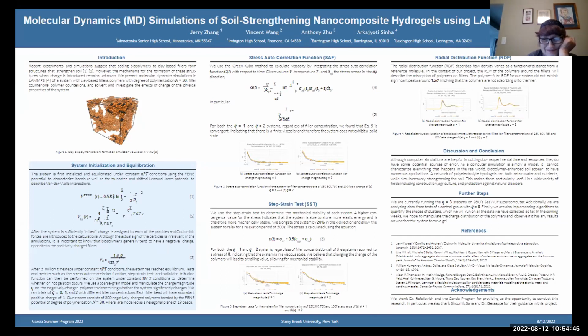Jerry. In addition to the experimental studies conducted on the use of biopolymers as a soil additive, our group seeks to characterize how charge induces the network formation of biopolymers and clay fillers using coarse-grained molecular dynamics computer simulations. In each of our systems, we initialize 5 types of particles: the solvent, the backbone architecture polyelectrolytes, the rigid multi-bead fillers, and the respective counterions to the polymers and fillers.